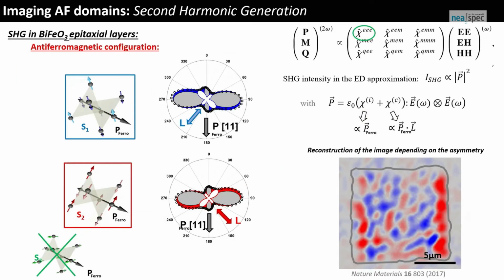And I will skip all this symmetry analysis, but if you look pixel per pixel at the angular dependence for the incoming polarization, you can note that there are two kinds of families, basically. You do a bit of symmetry analysis, then you can separate one part, the gray part, related to the ferroelectric part, and then the color part, which is related basically to L. So in the single domain, it's basically L. And if you reconstruct this asymmetry, you can have one image which gives you the antiferromagnetic ordering